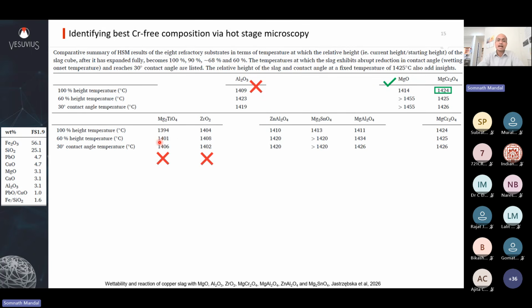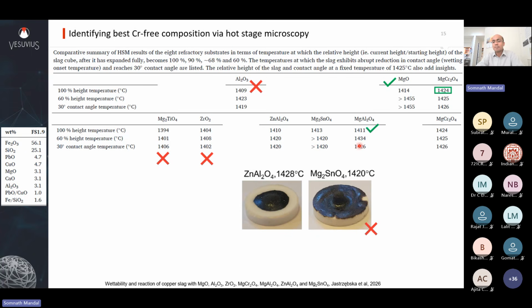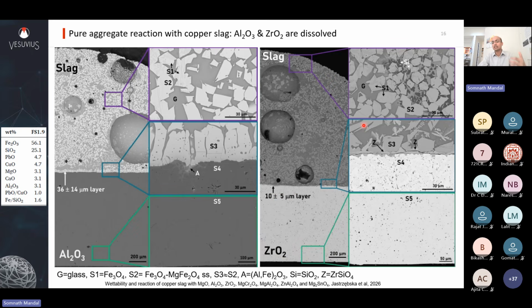Now from the candidate phases, you see that magnesium titanate and zirconia have very low temperature versus magnesium aluminate and zinc aluminate. Because of this, these are primary candidates as potential candidates, and you can see magnesia-chrome as a standard, a point of reference. However, upon observing magnesium stannate and zinc aluminate, which seem to be very close to each other. In fact, magnesium stannate looked apparently better, but from a post-test image, you can see that the slag has spread out pretty fast in magnesium stannate, which sort of aligns with the initial FactSage thermodynamic calculations that were done. So for sure, magnesium stannate is not a candidate, and zinc aluminate is a potential second phase to be used in your magnesia spinel bricks. So this gives you direction of what to use.